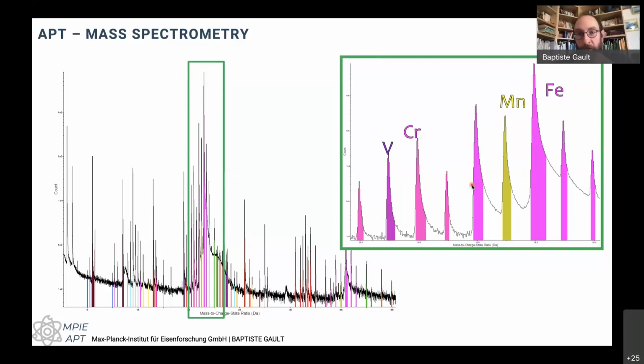So would that also be a problem for ceramics? It can be a problem for ceramics, yes. There's still work being done on ceramics, and some of it works really well, mostly on the instruments with the reflectron, so instruments that are much longer in time of flight. So you basically make these tails relatively smaller with respect to the peak. So it works fine.